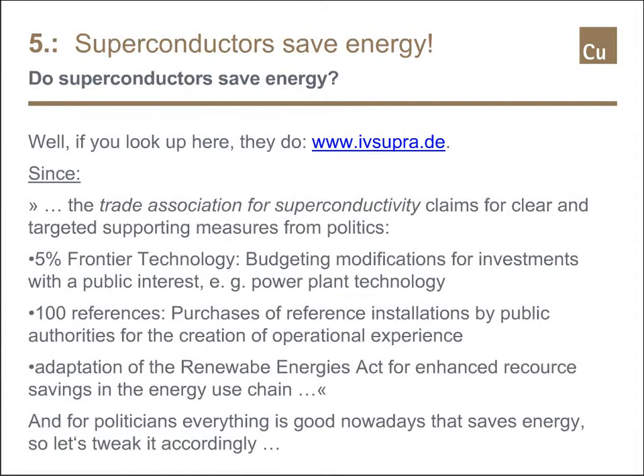The fifth type of conductors are the so-called superconductors, which lose all electrical resistivity below a certain temperature. Now, for many decades, this temperature limit was around 4 Kelvin, say minus 269 degrees Celsius, which limited their use to some very special applications. Until in 1986, I think it was, that so-called high-temperature superconductivity was invented, which means that you don't need 4 Kelvin, but already at 100 Kelvin, you can reach superconductivity with certain materials, which is still minus 170 degrees Celsius. Now, there are some applications which are enabled by such conductors, which are totally impossible to make with copper or aluminium, even with silver.